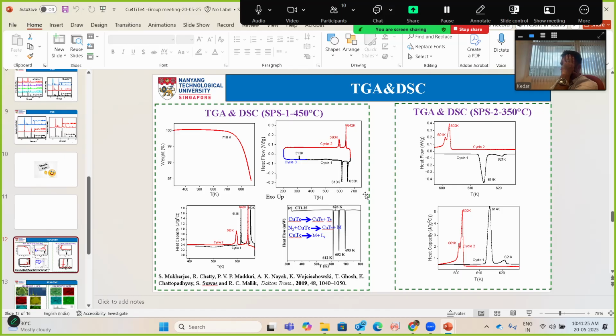Is that right? And at 300 Celsius, what you typically expect is your copper telluride decomposing into some copper telluride plus excess tellurium. Is that right? This is what people have reported, is it? And that's the bottom right curve, right? So what you're basically saying is that this 612 should be the same as this, and that's coming from these set of reactions. Is that what you're saying?